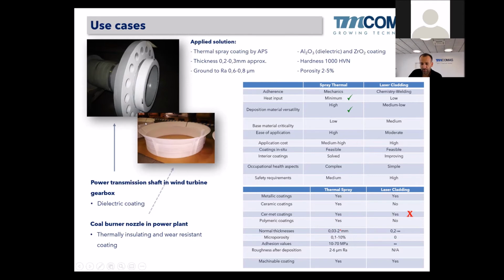And for the electric properties, we are using aluminum oxide. And for thermal insulation, we are using zirconium oxide-based ceramics. Hardness about 1,000 Vickers and porosity is higher because of the plasma spray. And in the case of thermal insulation, the parameters are set to create some porosity to improve the insulation properties of the coating. So at the end, the critical point here was the need of a ceramic coating, and if we need a ceramic coating, we have to use thermal spray.